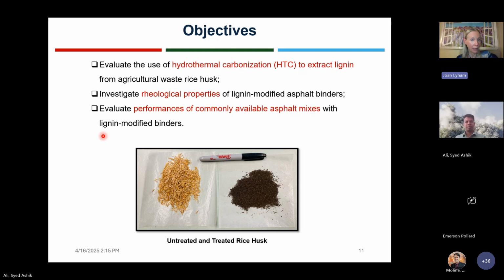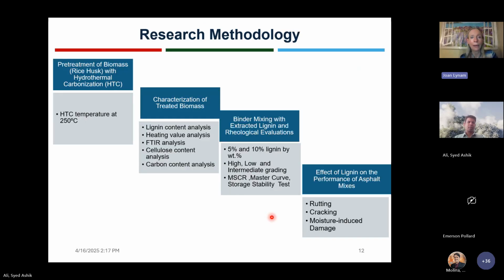All right, so we wanted to do HTC to extract lignin. We wanted to look at the rheological properties and the mixes, just as I said before. The picture you see is that on the left is what rice husks look like when they're not treated. And then on the right, you can see what it looks like after they're treated by hydrothermal carbonization. So we can go on to the next slide. And this is what our research methodology looks like.